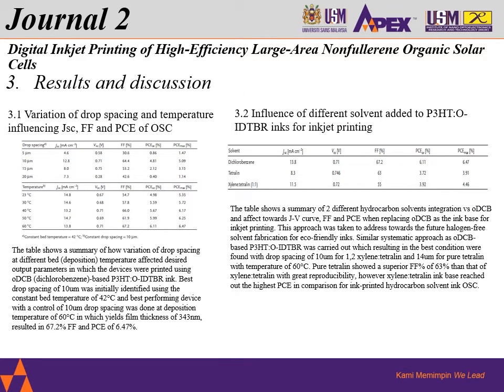Going to the results and discussion, I have a table of summary here. In this journal, there's a variation of drop spacing and temperature influencing the current density, fill factor, as well as the PCE of the OSC. Firstly, it was done with the same acceptor and donor mentioned before, but with ODCB or dichlorobenzene base. This is to find out first of all what drop spacing gives the highest PCE. What was done was with a constant bed temperature of 42 degrees Celsius.